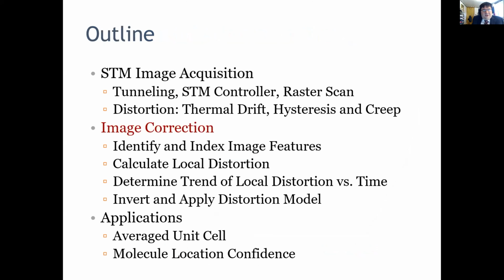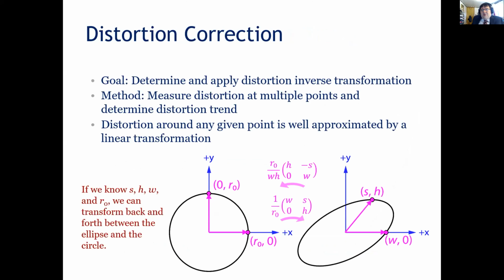So how do we do this image correction? We need to determine and apply the inverse transformation of the distortion. So we're going to measure the distortion at multiple points in the image to get the distortion trend with time, because we know the chronological order of the pixels. If we get distortion at a bunch of points in the image, we can plot them versus time and determine the time trend of the distortion. We know our nearest neighbor features in a lattice should lie on a circle. For our substrate, we are looking at graphite, so you've got 6 carbon atoms in a close packed grid.